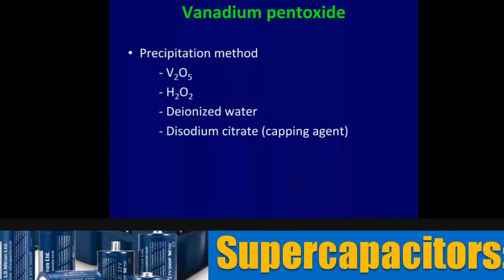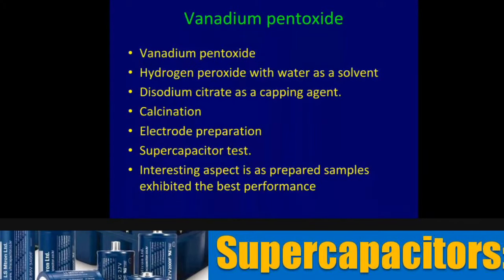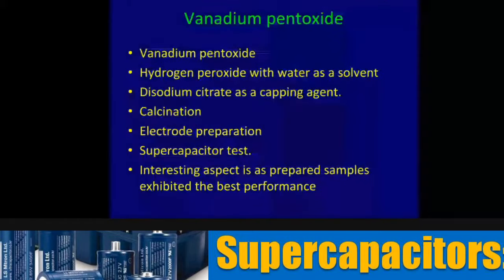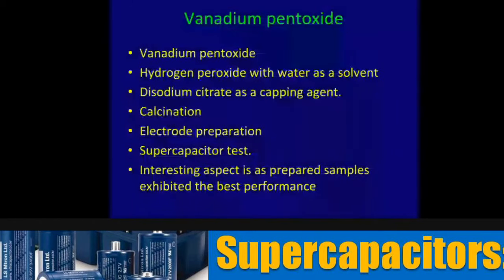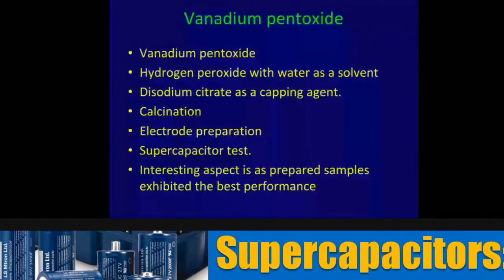You know that if the nanomaterial is left to itself, there is a process of aggregation and all that, which will spoil the performance. So disodium citrate is used as a capping agent so that the size variations are arrested. With vanadium pentoxide, we got excellent results. The interesting aspect is, unlike other materials where the performance improves only after heat treatment, vanadium pentoxide gave us very good results, because even the as-prepared material exhibited the best performance.